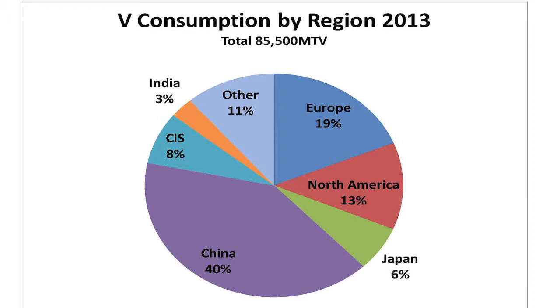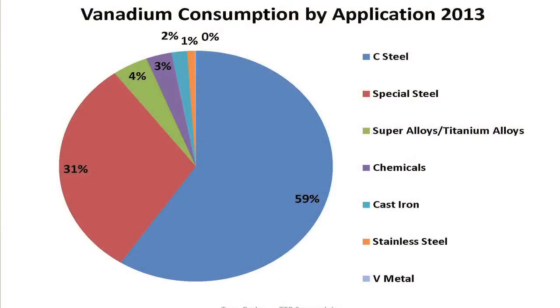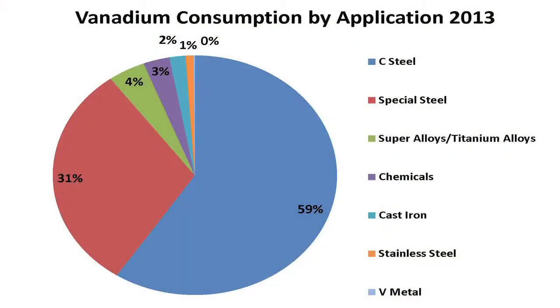Looking at applications, today about 90% of the vanadium in the world is consumed in the steel industry. And there's really two classes of steel that consume vanadium. Carbon steels, by adding a very small amount of vanadium, half a kilo of vanadium per ton of steel, in many cases we can double the yield strength of that steel and in essence double the utility of that material when we're talking about load-bearing applications. So carbon steels, we put a little vanadium in them and we have a class of steels called high-strength, low-alloy steels. That's the major application for vanadium today.